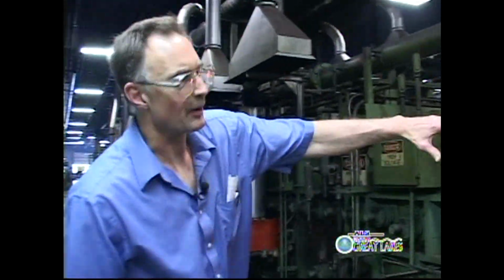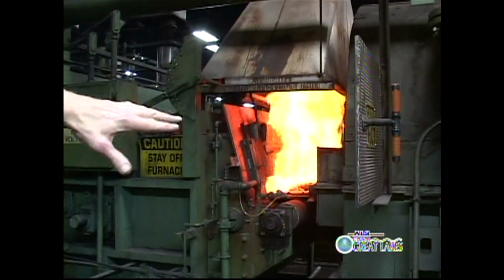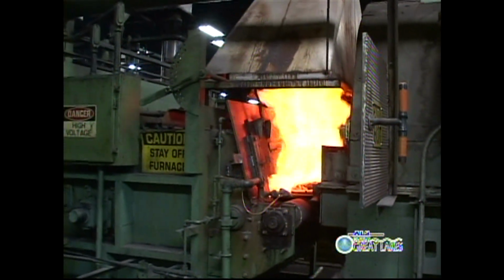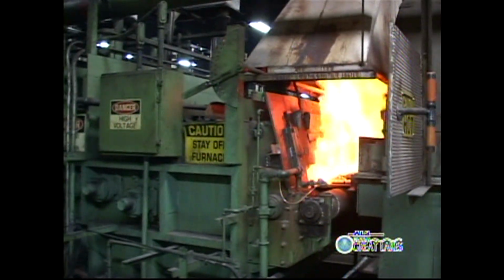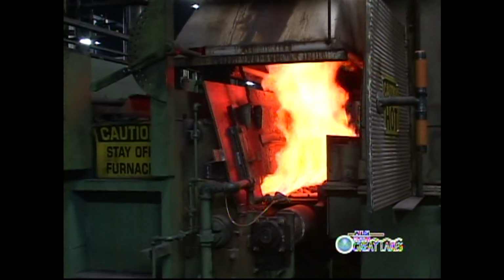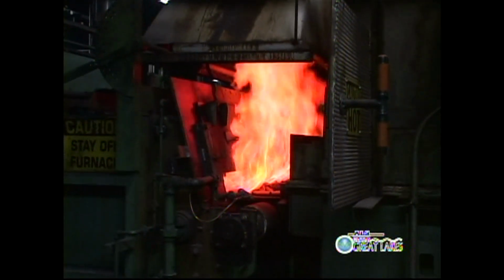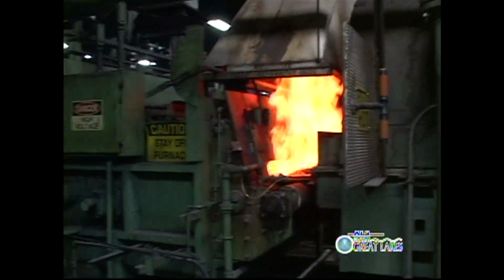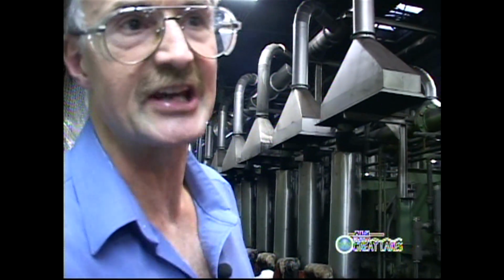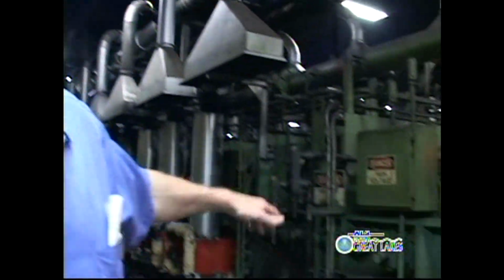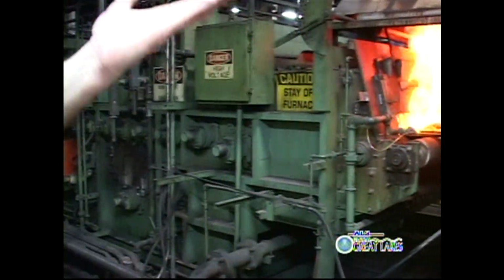This will preheat the parts to 750 degrees before they go into the beginning of the furnace. As you can see, the flame burning off here is endothermic gas. It's the protective gas, again, that we make here in our generators. This is the blanket gas for these belts so that the parts will not scale. We then control the carbon potential with natural gas and air.